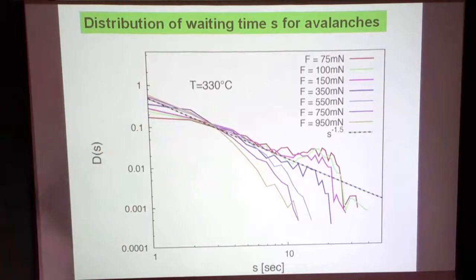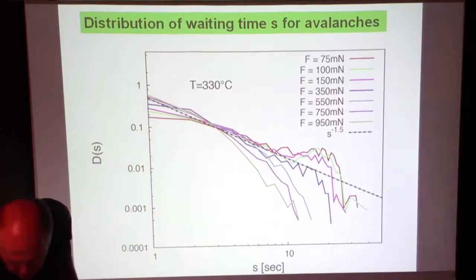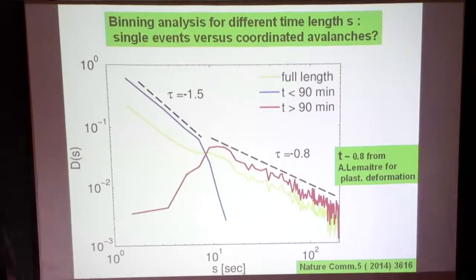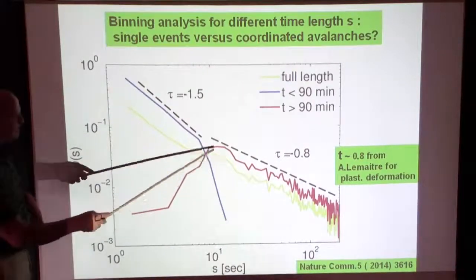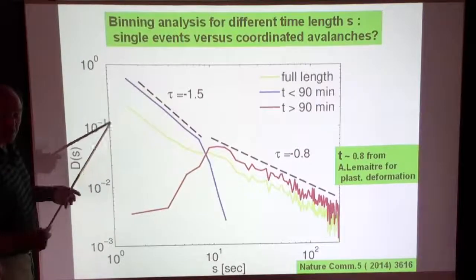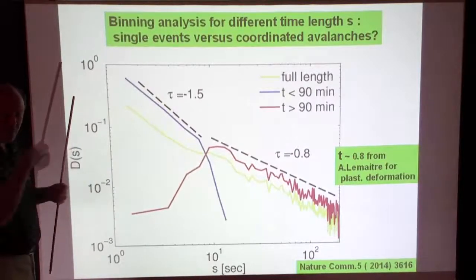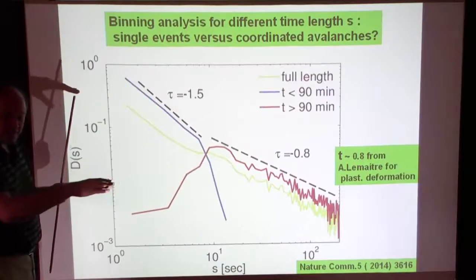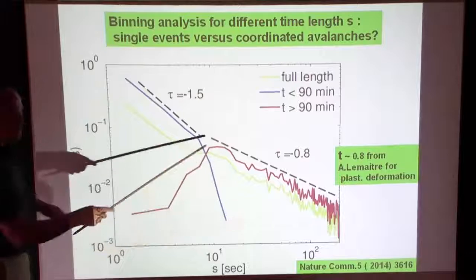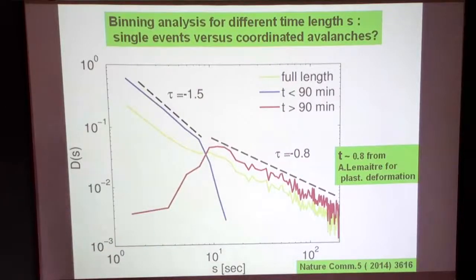Okay. Konrad, is this waiting time? Waiting time. It's not jump sizes. No, it has nothing to do with avalanche size distribution. It's not obvious. It's the avalanche. Well, we wait for waiting time. It's true, but if you had a big event, it's not unlikely that you've relaxed it for a little bit. The idea is that the waiting time is actually reduced, okay, to certain numbers up here for a normal event. If we have now a coordinated event, this takes much longer to take its place. So long waiting times means a coordinated shear band motion, which takes place then, takes much longer to wait for that.